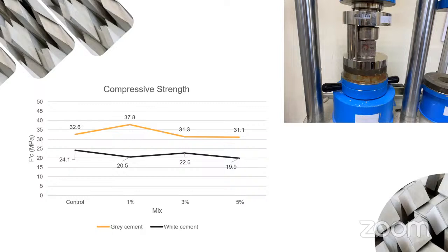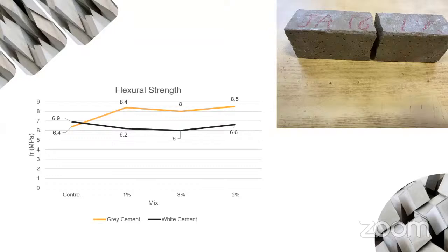We do not see the same behavior with white cement because it is mostly a decreasing trend. So the optimal percentage is 1% titanium for gray cement for the best compressive strength properties. In the next slide, we can see that approximately the same behavior was visualized with flexural strength.